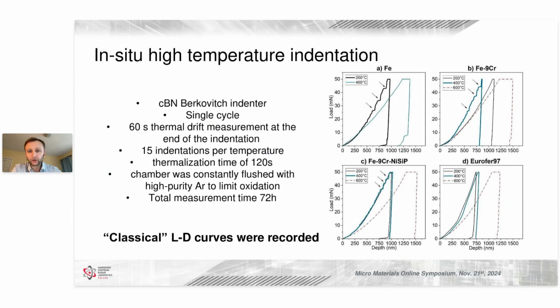So we did our nanoindentation using a cubic boron nitride indenter on model iron chromium systems and Eurofer 97. The measurements were done at 200, 400, and 600 degrees. They were repeated roughly 15 times. As I said, we used a chamber which was purged with high purity argon, just to limit oxidation. And the total measurement time per sample was roughly three days.